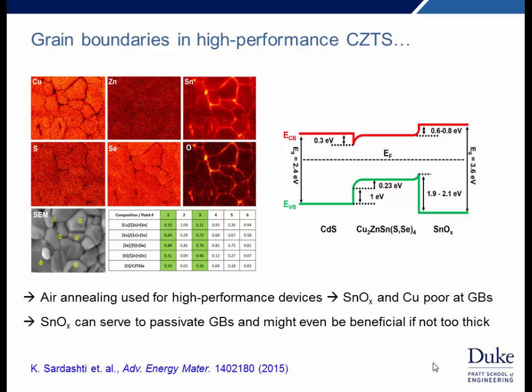Another thing we've examined is the nature of the grain boundaries. And one of the things we found is that air annealing substantially improves all of the device parameters. And we've looked at what is happening compositionally when we do this air anneal using nano-Auger. And the dominant thing that's evident here is that we have an enhancement of tin and oxygen at the grain boundaries. And so we're forming a thin layer of tin oxide at these grain boundaries.